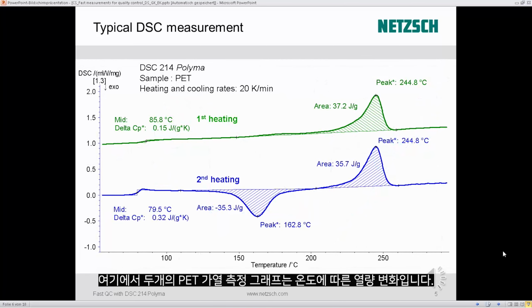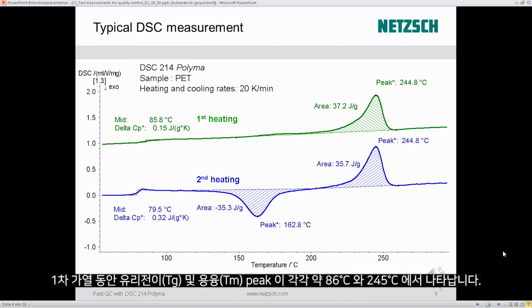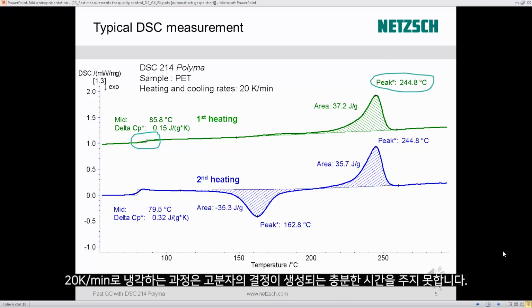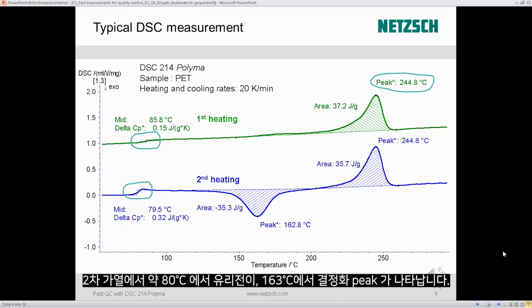Here, both heatings of the PET measurement are temperature scaled. During the first heating, the glass transition and the melting peak of PET were detected at 86 degrees and 245 degrees, respectively. During the cooling at 20 Kelvin per minute, the polymer didn't have time to crystallize. This leads to a bigger step of the glass transition in the second heating and to a crystallization peak found at 163 degrees.